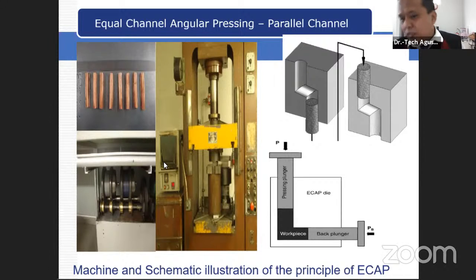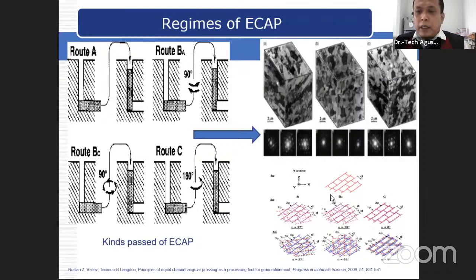It has been established that the optimal value of the processing parameters leads to large strain homogeneity in the cross section of the processed billet, up to 100 degrees. And for displacement, I think it's better if we use free displacement. Here, to produce variable mechanical properties and grain distribution, different ECAP routes are used. So we have four routes of ECAP processing.